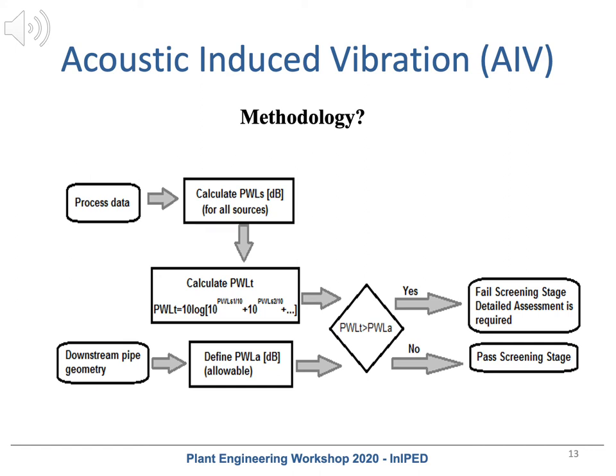The screening stage uses simplified and conservative methods to identify devices which can have a potential cause of acoustic-induced vibration failure in downstream piping. The objective of this stage is to safely reduce the scope of devices which require detailed assessment. In this stage, the sound power level at the source is compared with the most conservative allowable sound power level for the downstream line. For simultaneous relief cases, the total sound power level, resulting from combining all the sound power levels by logarithmic addition, is compared with the most conservative allowable sound power level for the downstream line.